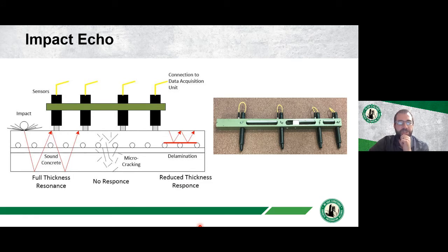Another thing we did on this structure is used impact echo to understand the quality of the concrete. So impact echo is an acoustic method where we make an impact on the concrete and it sends stress waves bouncing into the concrete. If the concrete is sound, those stress waves bounce with the full thickness of the slab. If there's a delamination, that reflection will occur shallower. And if there's a lot of cracking in the concrete, we may not get any reflections. And so we have this 4-sensor array that we use to assess the condition of the concrete.